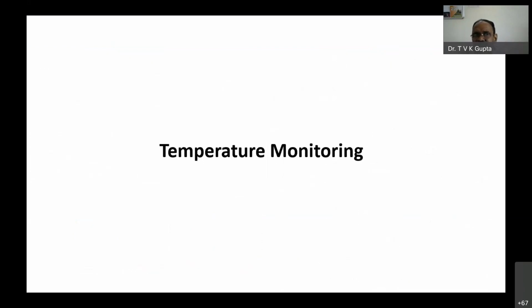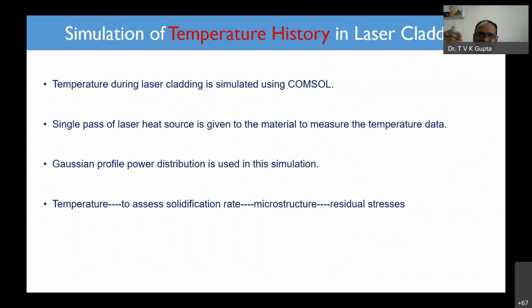Then we tried with temperature monitoring. In order to monitor the temperature, we have used pyrometers. Before that, we thought that we would be using some sort of simulation process where you can understand how the temperature is going to vary across the surface. So we have used COMSOL to understand the temperature distribution in the cladding process. We have used a single pass heat transfer source to the material, and to measure the temperature data, we have pyrometers, and the temperature through simulation we got, and whatever we got experimentally, we tried to simulate it.